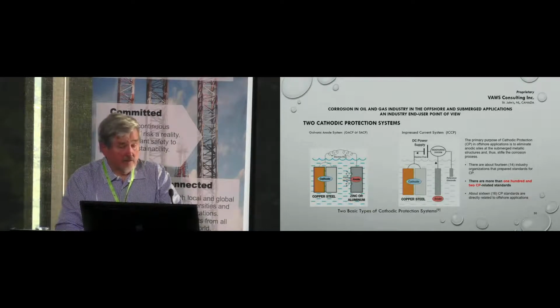Like you see that Russian pipeline, that pipe is so well coated, the sacrificial anodes will work on it. They predicted 50-year life on that pipeline. Well, it lasted less than a year, but hopefully they will fix it. With impressed current, you can work indefinitely. Depends how much current you use. And you have to have a source of current in order to operate the impressed current system, which is not available everywhere.